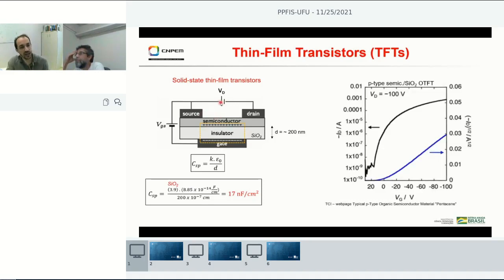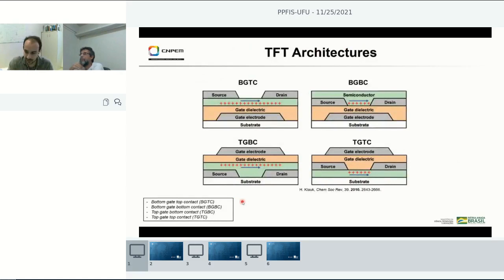So this means that when we operate a thin film transistor like this, we measure the current that flows through the semiconductor via source and drain electrodes, here shown in black for the absolute current values, and in blue for the current square root. And then when the gate voltage is high, negatively high, we induce larger amounts of current in the channel. Okay, I'd like to bring your attention here that in this kind of devices, we have typically voltages of tens of volts. Okay, this is because of this small gate capacitance.